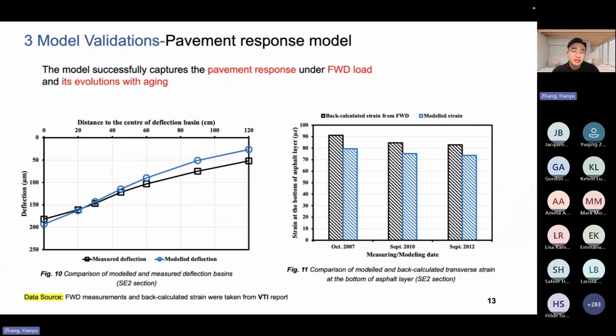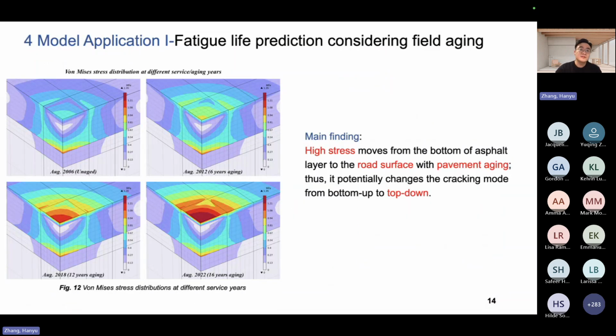So as we expected, and also shown in the right figure, we see with aging, the strain at the bottom of the asphalt layer decreases because we have a stiffer asphalt layer after aging. So after completing all the different parts of model validations, now we are confident to do some predictions, to have some applications of our models.